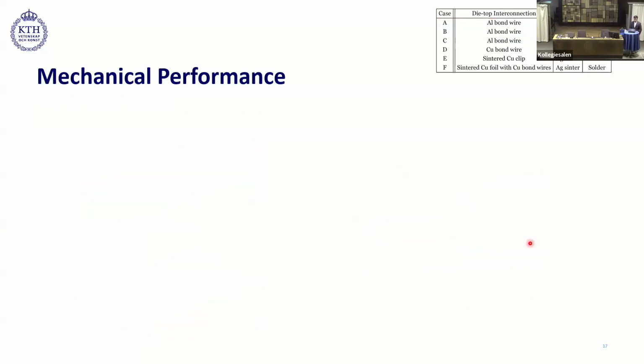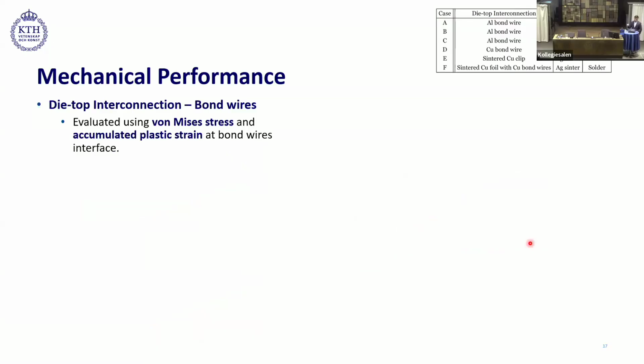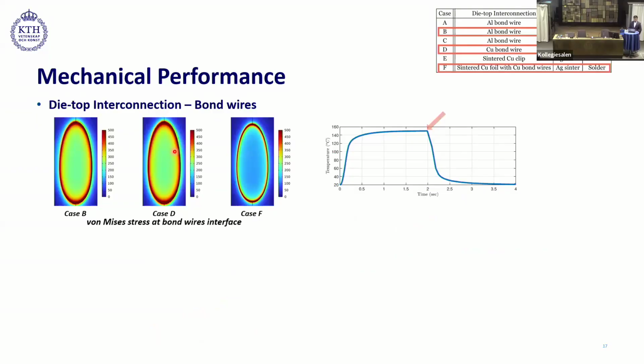Now we will go through the mechanical performance of the die top side interconnection. First, we will start with bond wires. So the performance of the bond wires was evaluated using von Mises stress and also accumulated plastic strain. Here, we are looking at the von Mises stress distribution on the surface of the bond wires. We see that aluminum bond wire in case B and copper bond wire in case D have higher von Mises stress at their surfaces. However, in case F, it's reduced, and that's because we are using a copper layer in between the die and the copper bond wire. I would also like to mention that these plots were plotted at the maximum junction temperature.